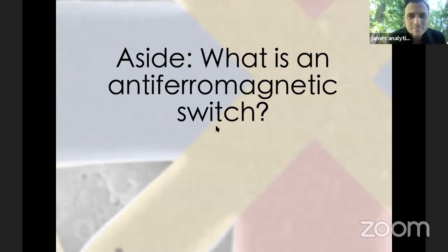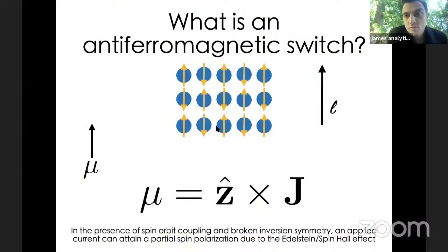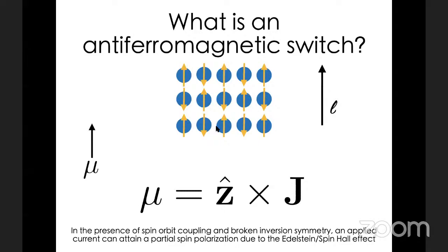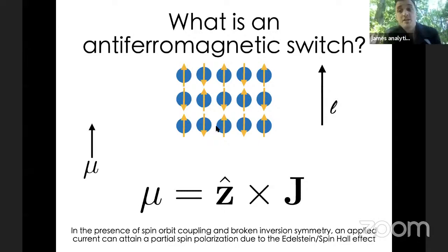Okay, great. For those of you who are familiar with this kind of work, you'll know that the basic idea is essentially inherited from the way we understand spintronics in the ferromagnetic context. But in this case, you have an antiferromagnet where the spins are staggered, let's say in the square lattice. And from the difference of the sublattice magnetization, you can define what's known as the Néel vector, which points in one direction. And the whole idea is that, let's say your system breaks inversion symmetry, so it either happens at an interface or the system breaks inversion symmetry in the bulk.